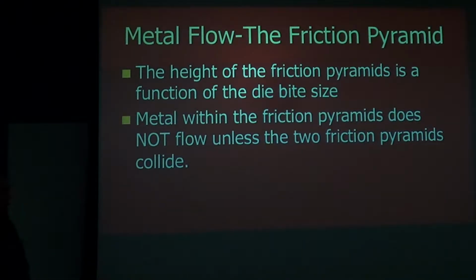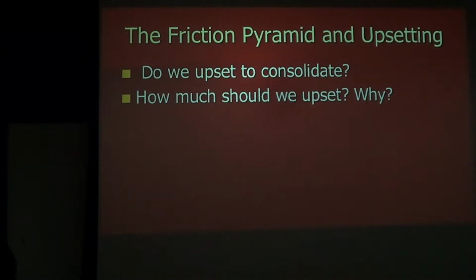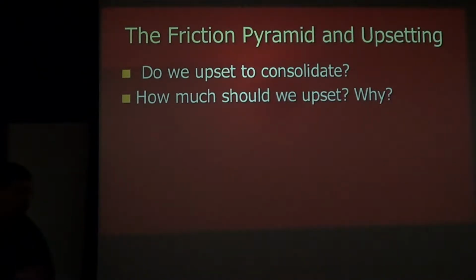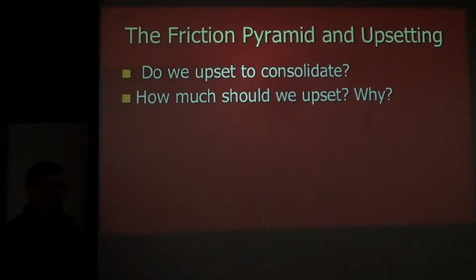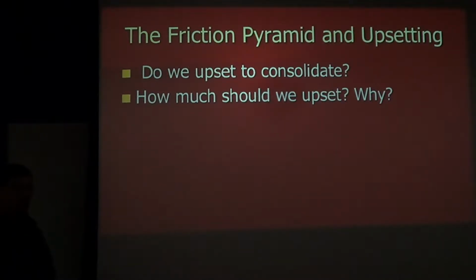So we want to talk now about how do we make that happen. What are the forging conditions that we have? What goes on in those situations? So I mentioned a little bit back this term upsetting, where we take an ingot and we shorten its length, right? So that's one way of forging. And because we do upsetting quite a bit as part of the forging process, we want to know, is that going to help us close up shrinkage cavities or not? And if it is going to, is there some critical parameter or critical amount that we need to have as a minimum for that to happen?